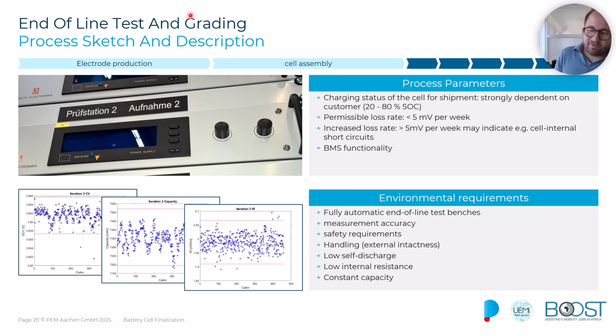Then typical tests for the internal resistance, they could do, for example, a DC IR test by applying a short pulse of a current, measuring the voltage drop, or an AC impedance test. So there are different opportunities to test the internal resistance. A pulse test can also yield the DC resistance, AC tests in the end yield the impedance value. And of course, this is crucial for the power performance grading of the cells in the end.